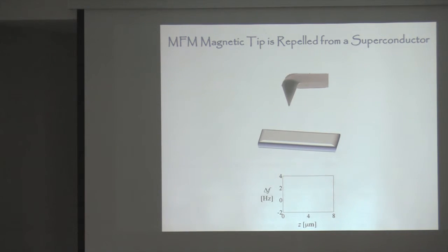Okay, so the first thing that you can do is just find a clean spot and bring your tip towards the sample and measure the resulting signal. So in a superconductor, you get something like this. We call this a touchdown curve. And this signal, if you think about it, means that you have a repulsion, stronger and stronger repulsion of your magnetic tip as you get closer to the sample. This is the result of the Meissner effect, because your tip is magnetic and it's being repelled from the sample. So this tells us that this is a superconductor.